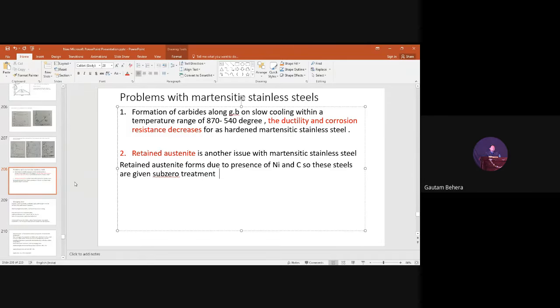So you people are getting the point now why high carbon steels have more retained austenite, because carbon is an austenite stabilizer. So that is one of the points. It tries to stabilize the austenite phase. So that means it will decrease what? Eutectoid temperature, obviously. So carbon also decreases the eutectoid temperature. Nickel also decreases the eutectoid temperature, and the A3 point also goes down. You understand?